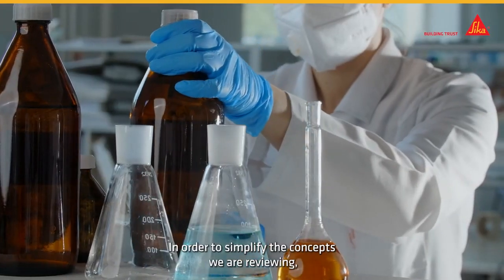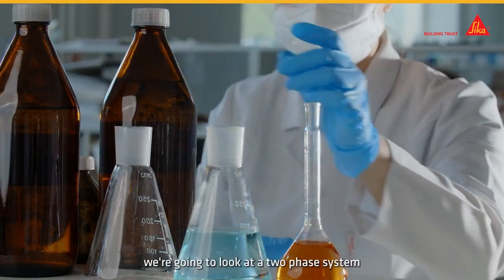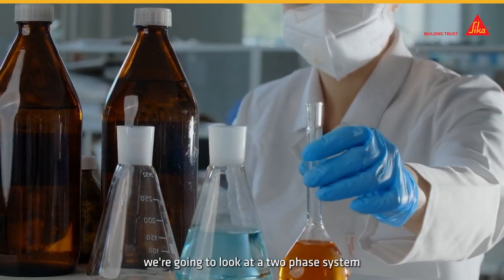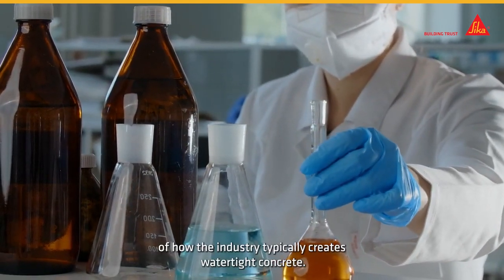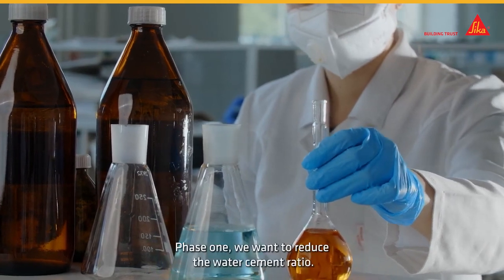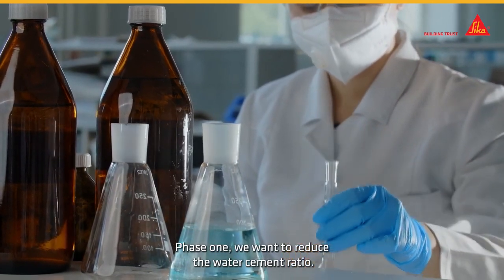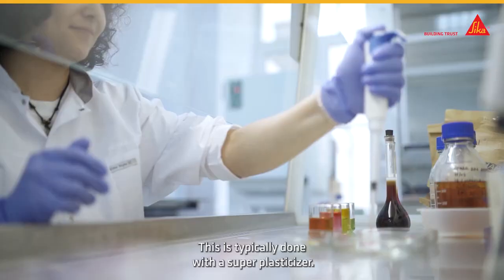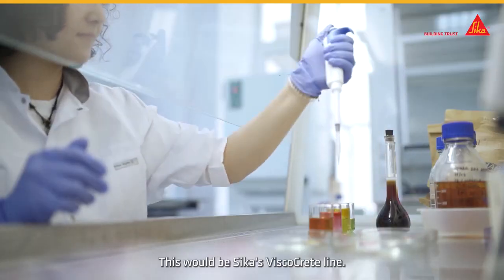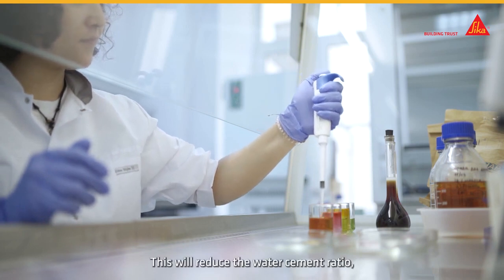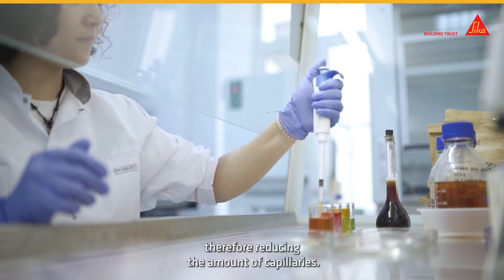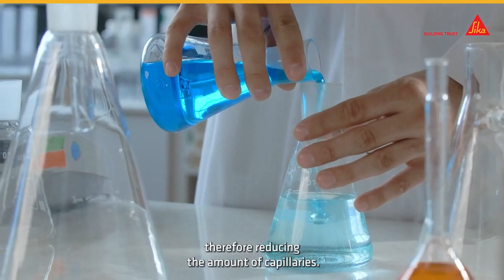Hydrophobic will repel the water from the surface. In order to simplify the concepts we are reviewing, we're going to look at a two-phase system of how the industry typically creates watertight concrete. Phase 1. We want to reduce the water-cement ratio. This is typically done with a superplasticizer. This would be Sika's Viscocrete line. This will reduce the water-cement ratio, therefore reducing the amount of capillaries.